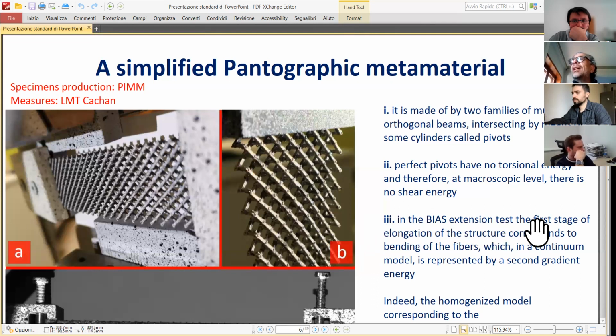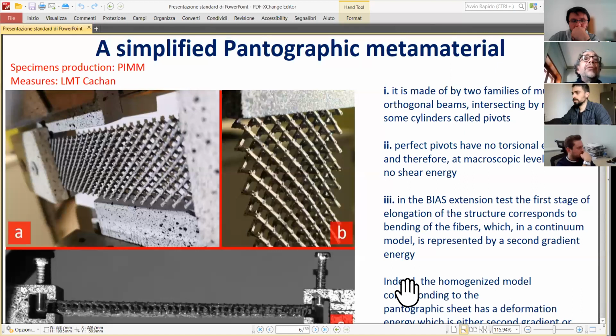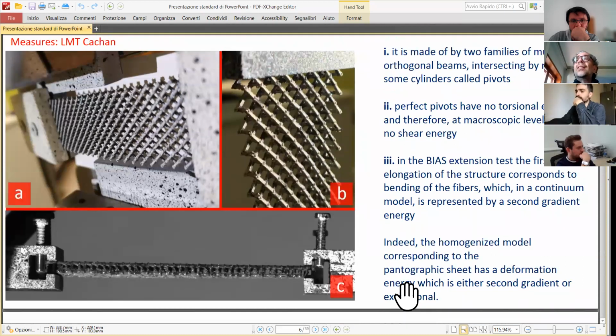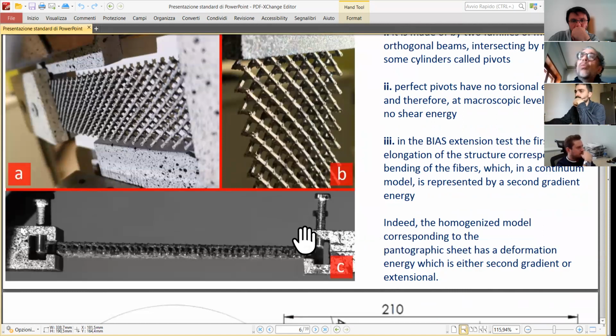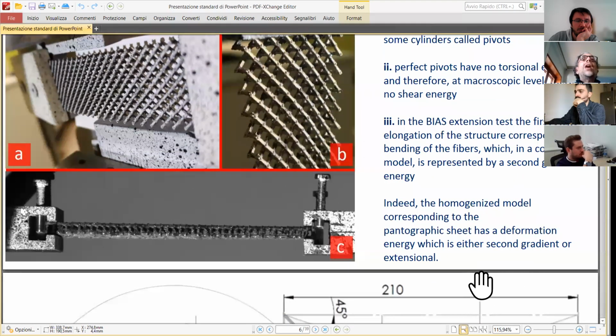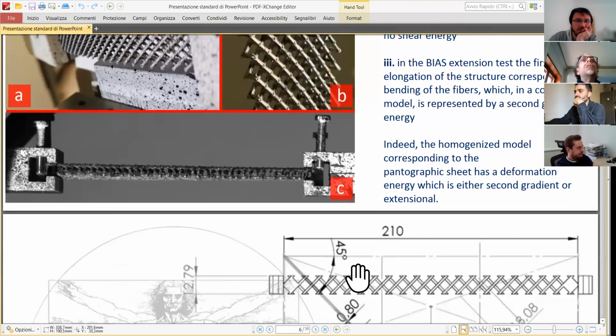In the bias extension test, the first stage of elongation of the structure corresponds to bending of the fibers, which in a continuum model is represented by a second gradient energy, which is rather unusual. In the deformation energy, you have a second gradient of displacement, which is rather rare in the literature. Why is all this happening? Because the homogenized model corresponding to the pantographic sheet has a deformation energy which is either second gradient or extensional. So either you have an energy related to the second derivatives, bending of beams, or you have an elongation of a bar constituting the system.